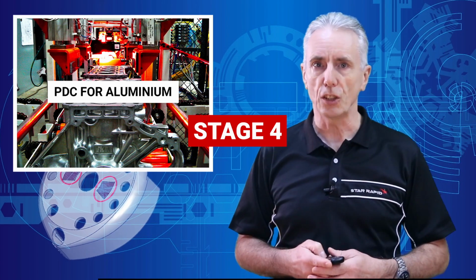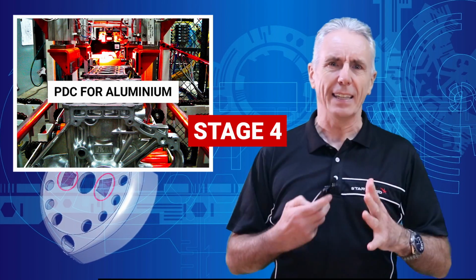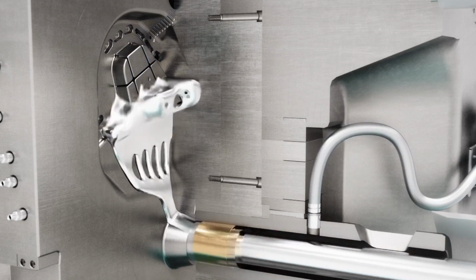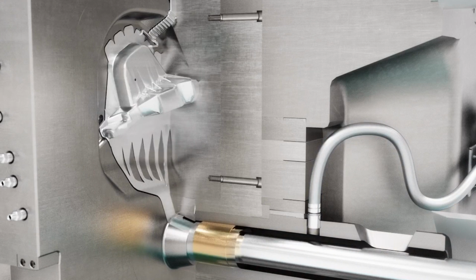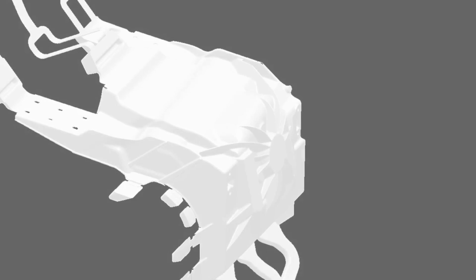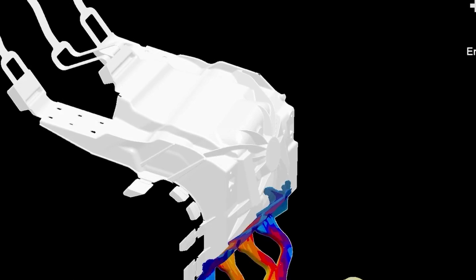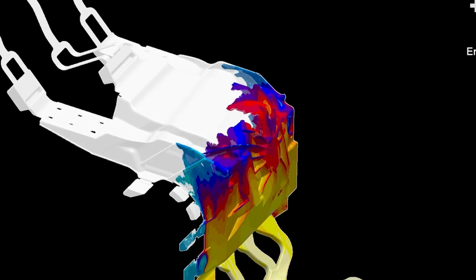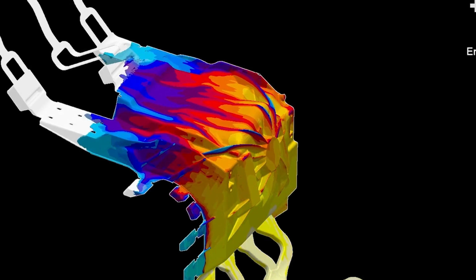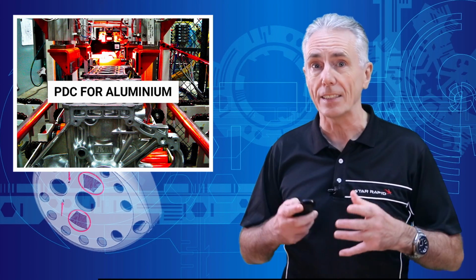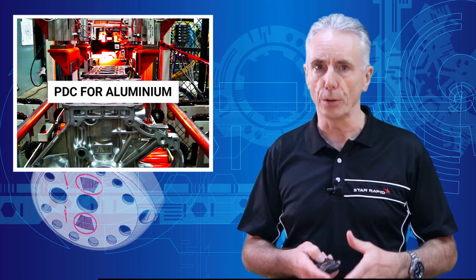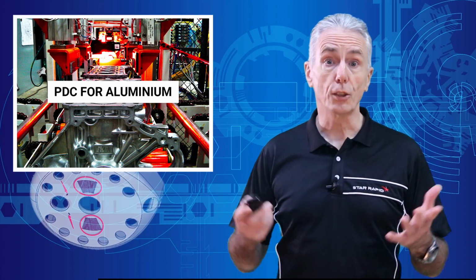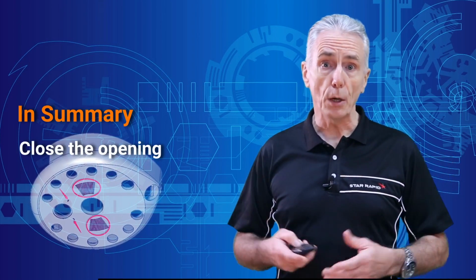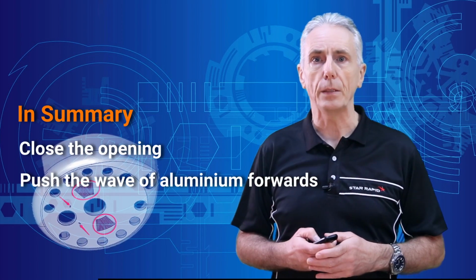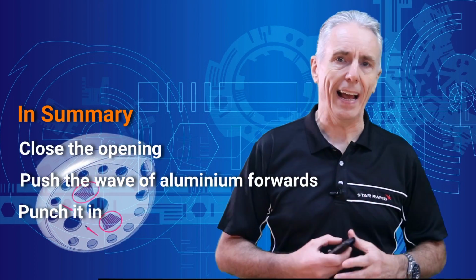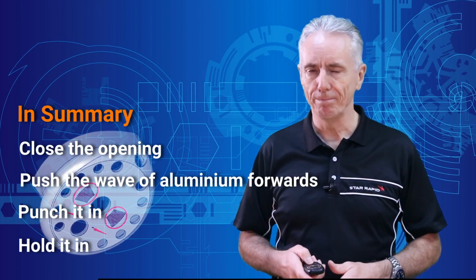And then finally, stage 4, is what we call the high pressure hold. This final stage is designed to make sure that the metal is pressed out into the tiniest reaches of the die, helps to backfill the material as it starts to crystallize and shrink in its slush phase, and helps to squash some of the entrained air that gets trapped into the melt flow during injection. Whew! So, in summary, close the opening, push the wave of aluminium forward, punch it in, and hold it in.